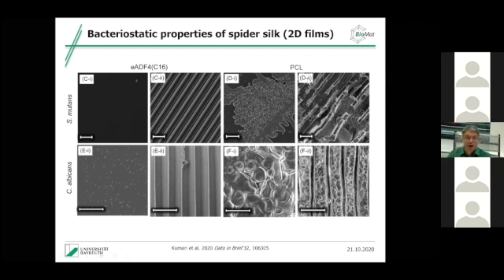And here you see one of our control materials, which is polycaprolactone, a very often used polymer in biomedical applications. Here we just tested bacteria like Streptococcus mutans, and down there we actually tested a yeast, Candida albicans. And as you can see, nothing is growing on the silk surface, no matter if it's a flat surface or if it's a structured surface. In contrast, on the polycaprolactone, you see huge areas covered with bacteria or with yeast, and this is what we call a biofilm. So we see immediately after a few days biofilm formation.